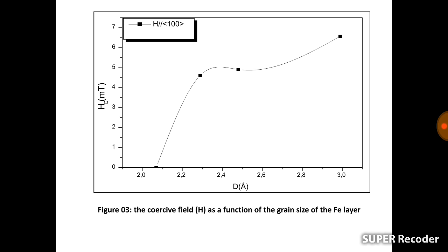It is also observed that the grain size increases. The quality of surface and interface is affected by the increase in the value of lattice mismatch between the layers, or the deformation translates into the presence of roughness in the surface and the interfaces of the layers, which leads to the increase in the values of the coercive field to a maximum value corresponding to the sample with the largest grain size, which is known for its poor quality. The increased coercivity suggests that the magnetization reversal process was associated with magnetization rotation and domain wall motion at the same time. So we deduced that the magnetic results are indeed equivalent to the structural results found by X-ray diffraction.